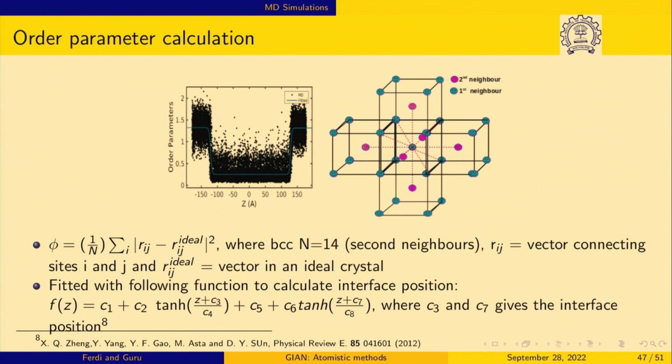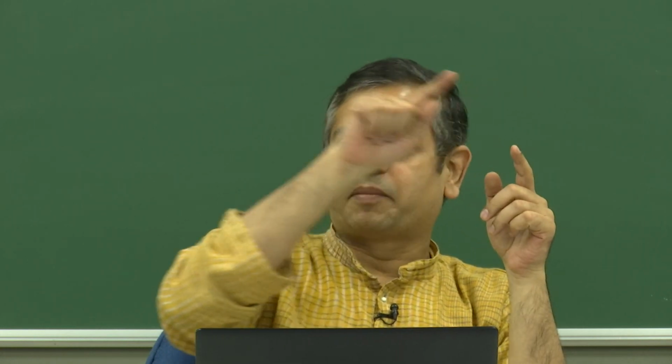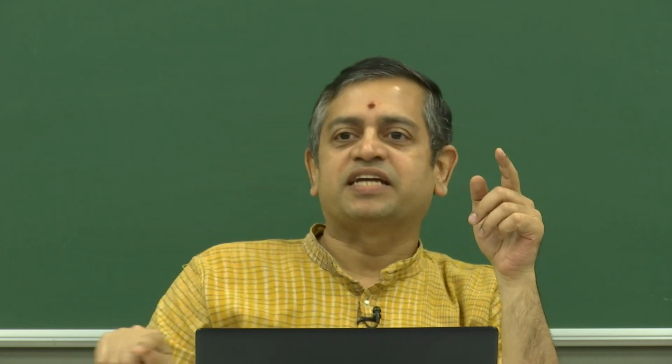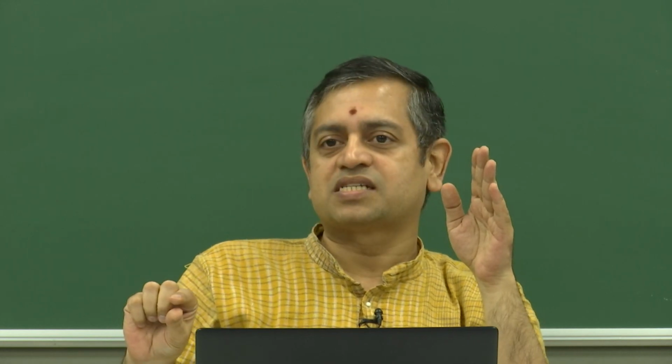Now, sir, the second part. I want to know how you are calculating the D. Are you calculating it by fitting parameters? No. I fit this binned data to get the curve, which is shown in blue. I do not know if you can see it. That blue line remains constant, changes, remains constant. So I just need to go to the point where it is the same constant on this side and the same constant on that side. We found that that happens to be about 10 angstroms.